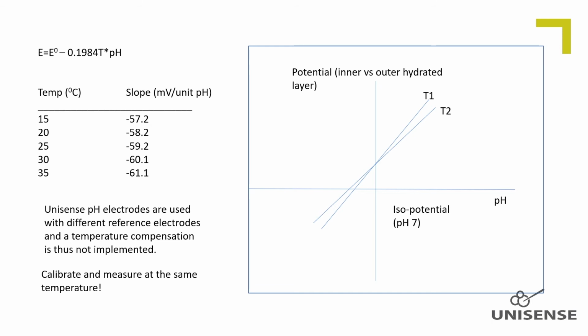Within a few degrees Celsius change, and especially at near neutral pH values, the interference is below the detection limit. Only at pH values far from neutral and at several degrees Celsius change is the interference above the detection limit. Not only the pH electrode response, but also the reference electrode and its liquid junction will be affected slightly by temperature. Because Unisense pH electrodes are used with different reference electrodes, we have not implemented a temperature compensation. Therefore, calibrate and measure at approximately the same temperature.